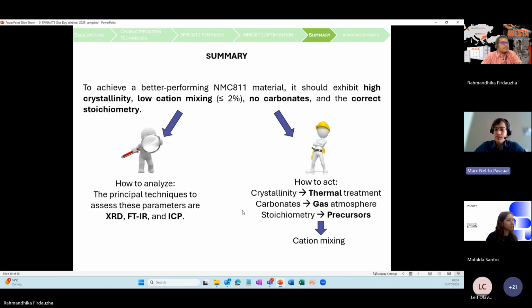For the crystallinity, the best way to do that is the thermal treatment. Remember from the first slide that I showed this SEM imaging and the crystallite size. In order to improve this crystallite size, what we did was increase the temperature, and the crystallite size increased considerably. Then for the carbonates, the best way to remove them is to tackle the gas atmosphere, to go for a gas atmosphere without carbonates, without carbon dioxide. And also, if you can go for oxygen, it's even better, as you saw from the lithium nickel cation mixing. And lastly, the stoichiometry should be assessed in the precursor solution. And in the end, if you assess all these parameters, crystallinity, carbonate, and stoichiometry, you will end up with a good lithium nickel cation mixing, which is what makes the material work as expected for an NMC811 material.